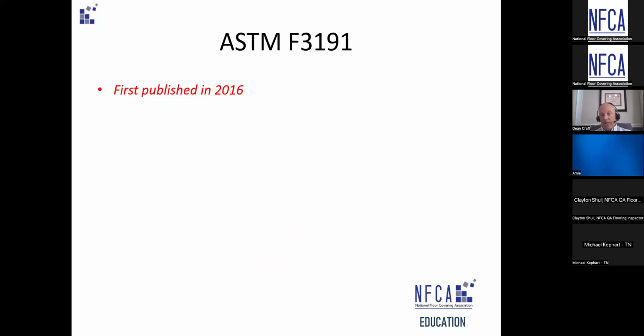I'm a big fan of bond tests. I think any installer that doesn't do them is missing an opportunity. Huge fan. And basically the standard is do whatever test the manufacturer says. In the absence of that, you've got F3191, which is a great ASTM: put a sample down, minimum 72 hours, go back, pull.